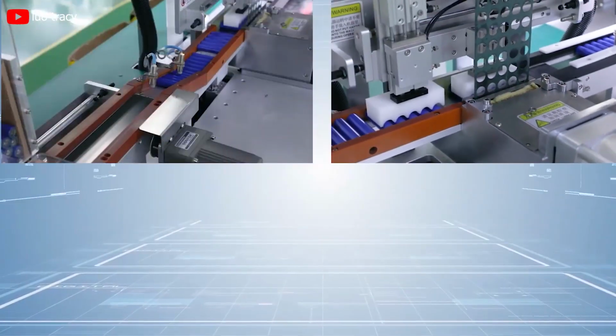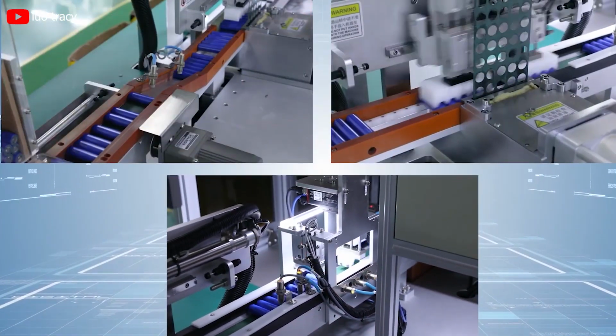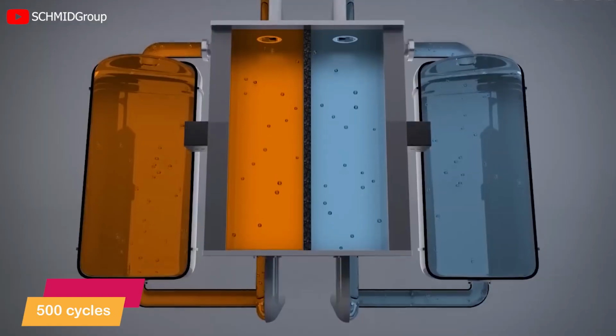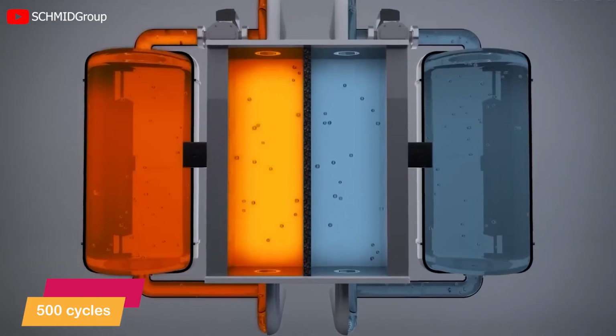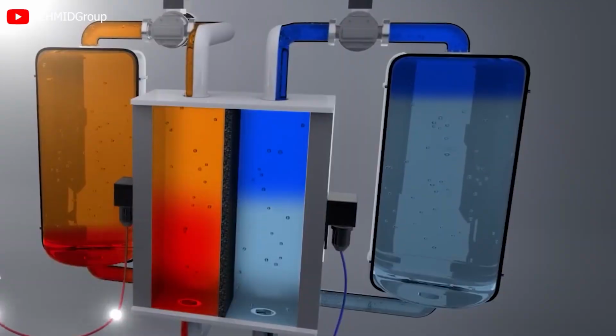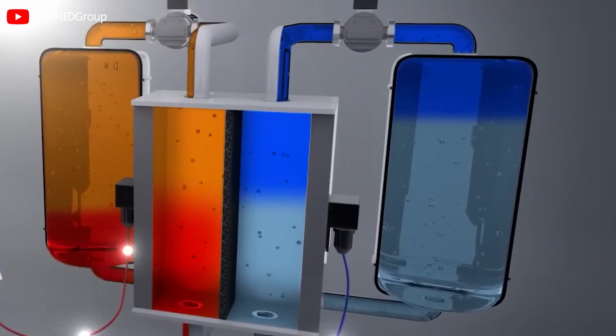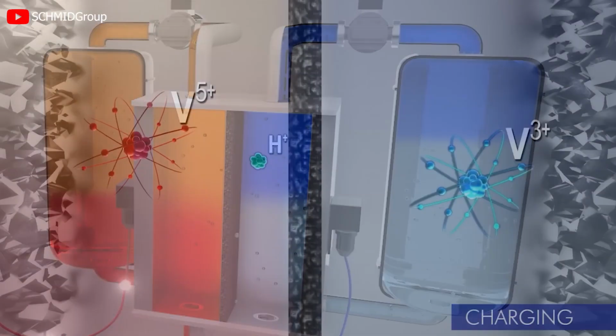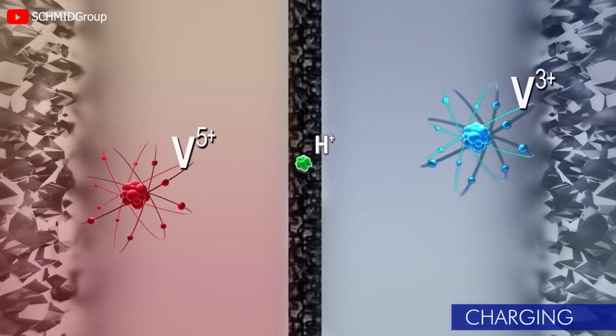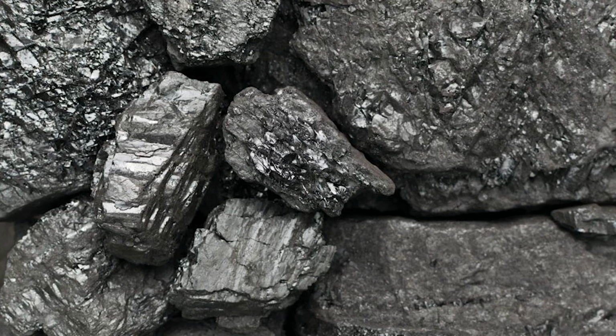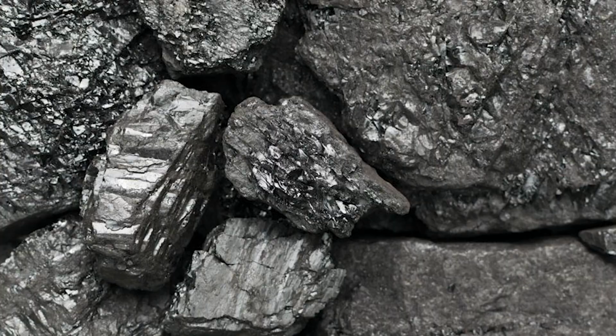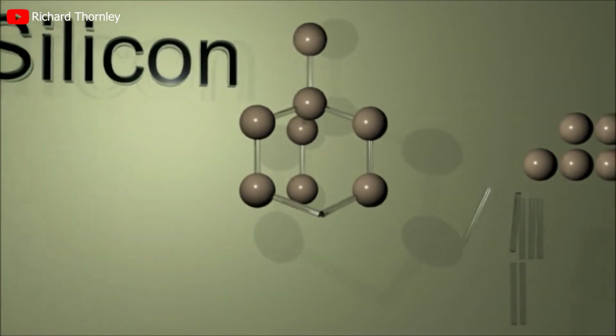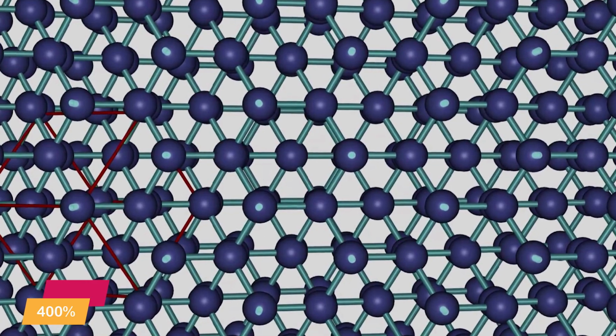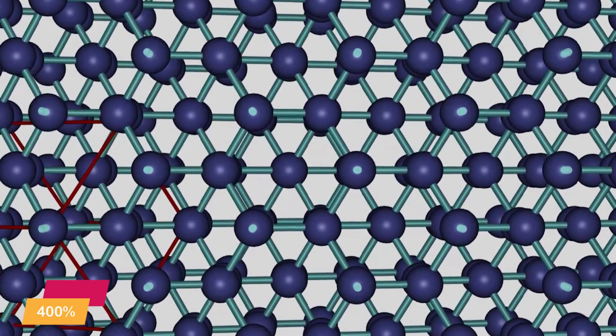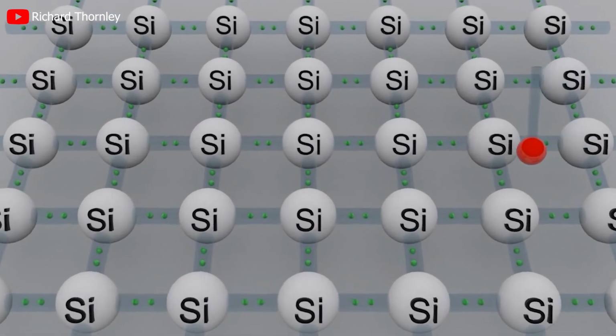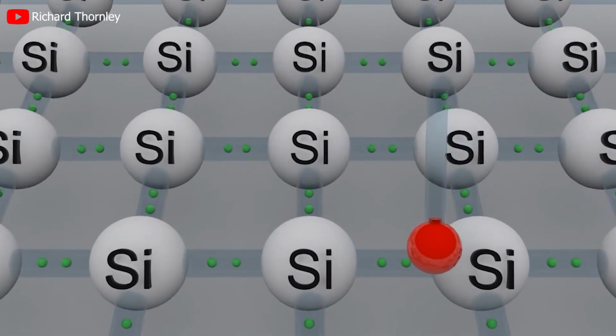Moreover, the utilization of silicon anode batteries preserves 80% of their capacity even after undergoing 500 cycles of recharging and discharging. This characteristic contributes to faster charging and discharging rates, ultimately enhancing the overall energy density. However, it's important to acknowledge that unlike carbon, silicon does possess inherent properties, such as lattice structure expansion by up to 400%, which presents certain challenges and considerations in its implementation.